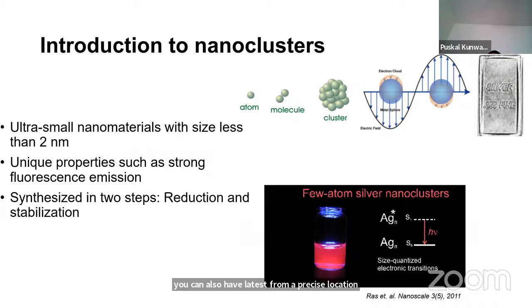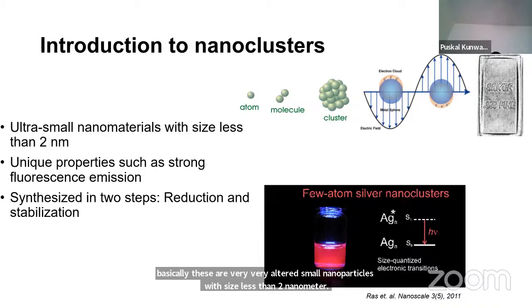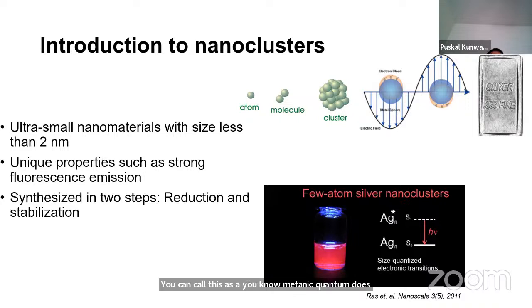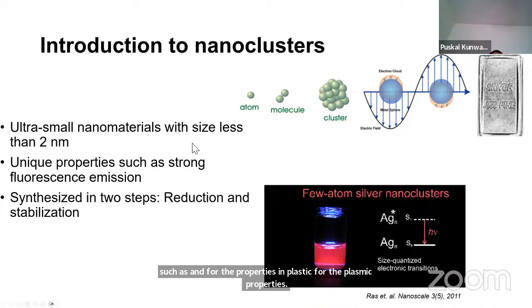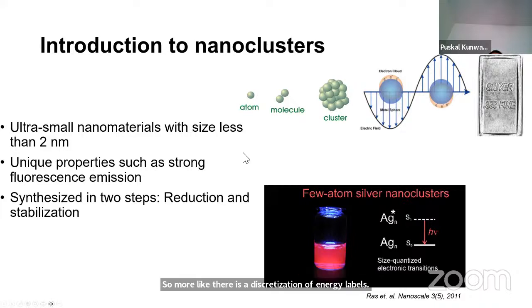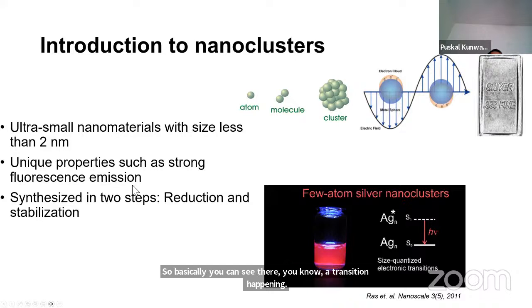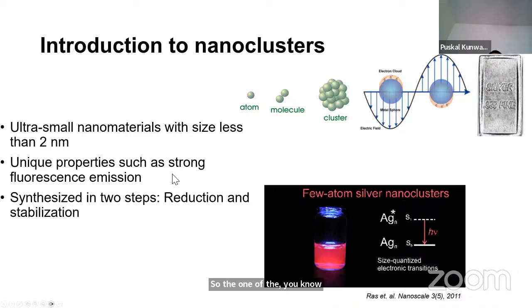Now we did a direct laser writing of nanoclusters. So what are these nanoclusters? These are ultra small nanoparticles with a size less than 2 nanometers. You can call them metallic quantum dots also. Since the size is less than 2 nanometers, there are not enough electrons for collective oscillations and plasmonic properties. Instead there is a discretization of energy levels, so you can see a transition happening. One of the unique properties of these nanoclusters, like semiconductor quantum dots, is that they have a strong fluorescence emission.